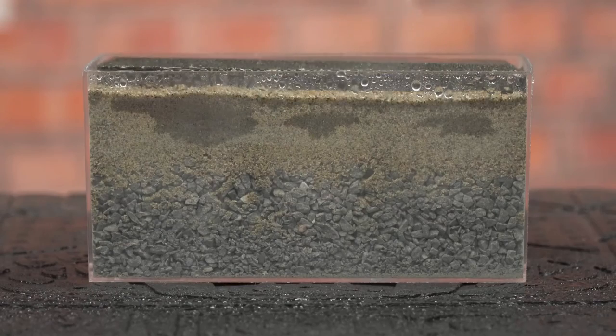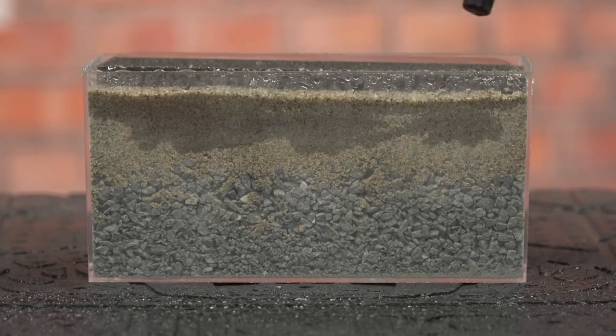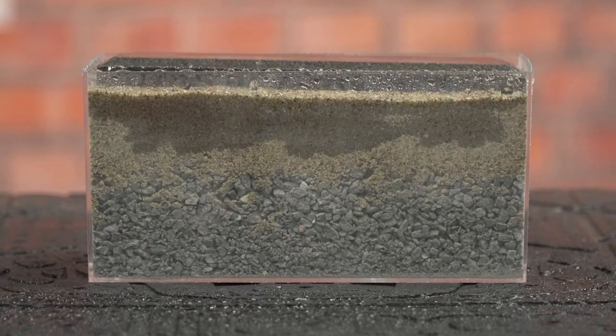So let's take a look at proper watering, right? Let's get enough water into that joint. We're going to water this down and really soak it well and make sure that we get as close to that entire joint saturated as possible, right? Get an inch and a half down, really get that polymeric sand activated so it can form a nice solid crust. And for such a small area, you really dump a considerable amount to achieve that crust.